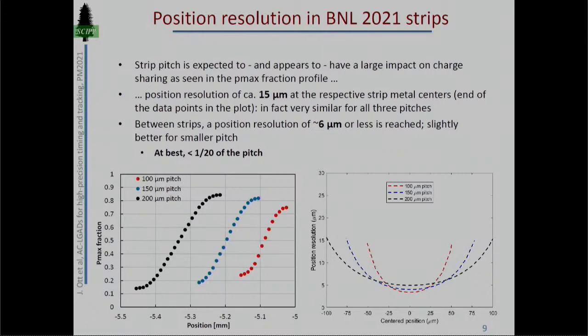But actually, when we look just from strip center to strip center, these are actually quite similar. So even a 200 micron pitch strip provides around 15 microns of resolution. That's by a factor of 5 or 6 better than in a conventional readout, where you're limited by pitch divided by square root of 12.